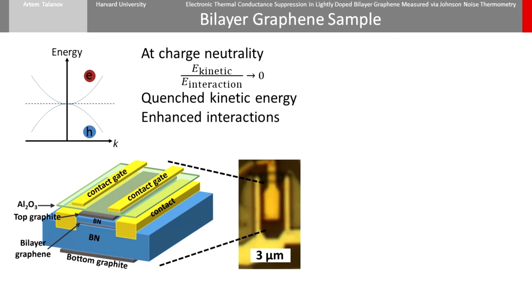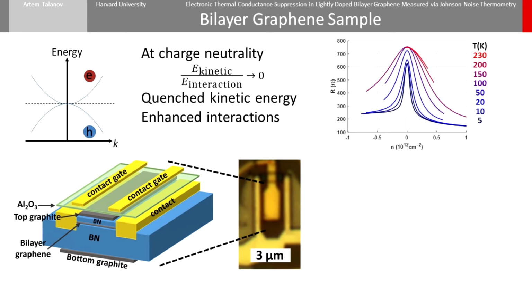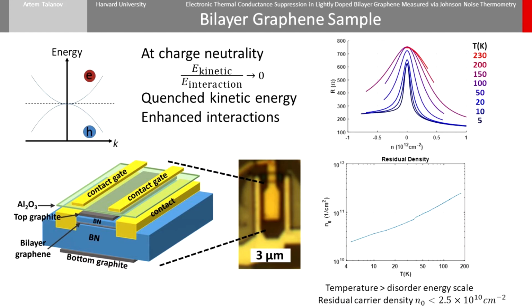How can we judge the cleanliness of the device? We examine resistance curves for various temperatures. As we lower the temperature, the peak at charge neutrality continues to get narrower. At each temperature, we can assign a density, called N0, that is characteristic of the width of the peak and represents the number of free charges at charge neutrality. For our entire measured temperature range above 5 Kelvin, the density decreases with decreasing temperature. This means the residual density consists of thermally excited electrons and holes rather than disorder-induced charge puddles.